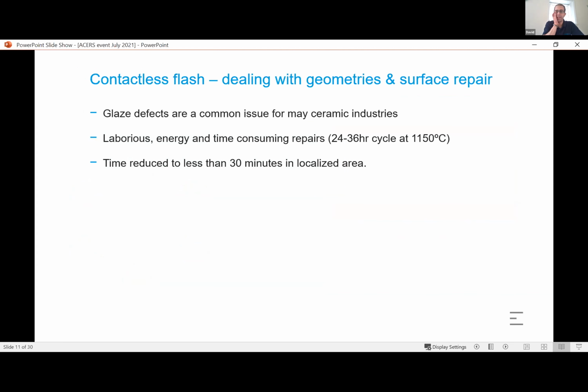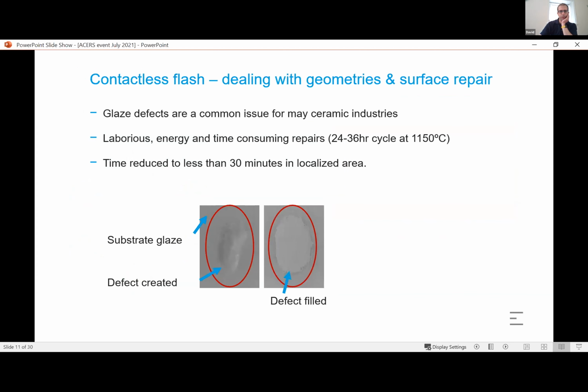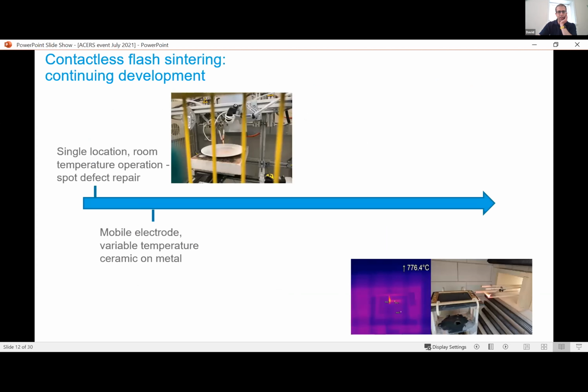I'll breeze through so I catch up on time. But if we think about where we can't use it in a contact area, but we want to ignite a plasma and raster over the surface. So we looked at repairing glazes, where you might drill out a defect, fill it with glaze, and actually lower an electrode, pass an electric field across to melt that and manage the thermal differential. Now, this would reduce the need for an entire refire kiln potentially, so significant carbon savings there.